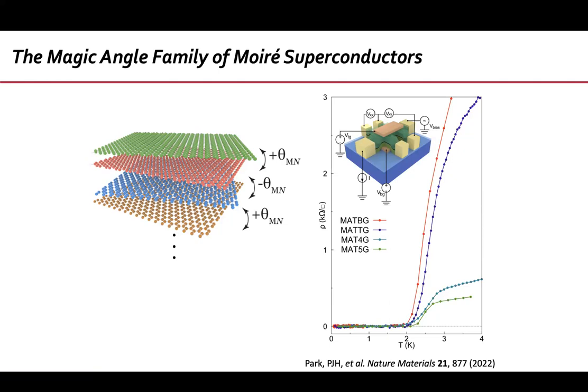In fact, we can measure all of this as a function of density, and the superconducting coherence length and the interparticle distance track each other and are pretty much the same in the relevant regime. This is all in this paper. The numbers in nanometers: it's about 10 nanometers, which is the same as the interparticle distance and the moiré itself. In the bilayer it's over 40, 50 nanometers, a bit larger.